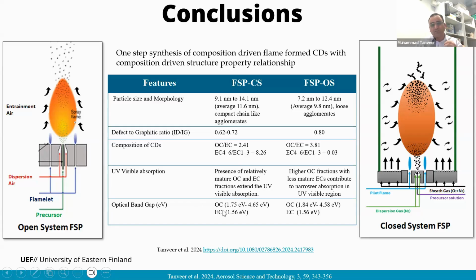And the band gap for OCs lies between 4.65 to 1.75 electron volt for the closed system and 4.58 electron volt to 1.84 electron volt for the open system. But the EC shows quite a similar band gap for both systems because this is related to EC2 to EC3. That shows quite a narrow band gap, around 1.56.